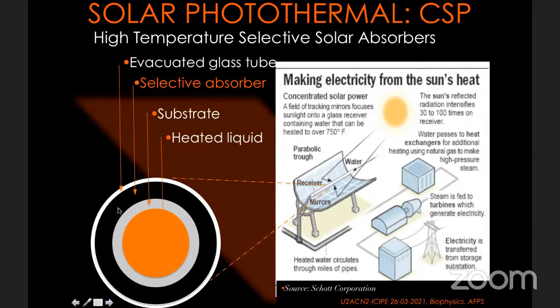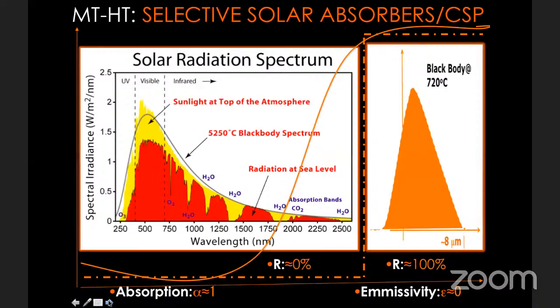So the design is to have a black material, and that black coating should have a low reflectance in the visible and the near infrared, and a higher reflectance in the far infrared. So it means it has to have a high absorption in the visible and a low emissivity.